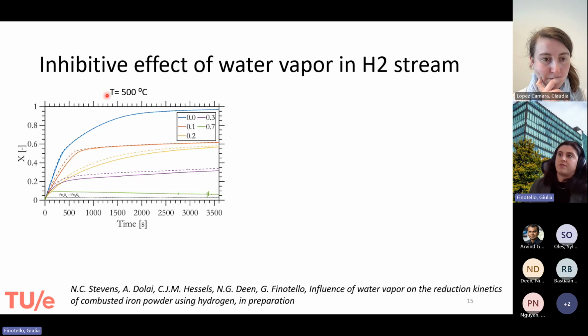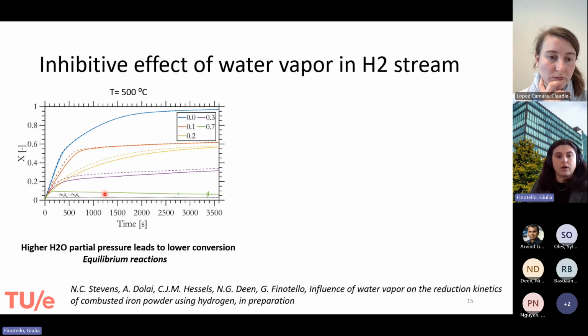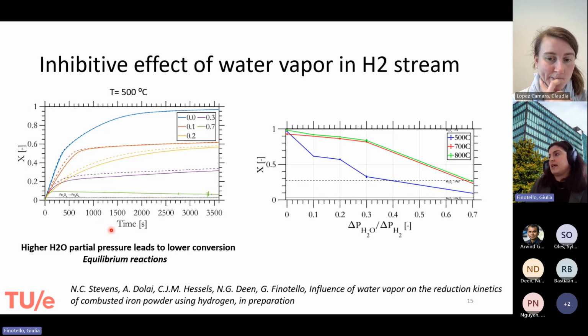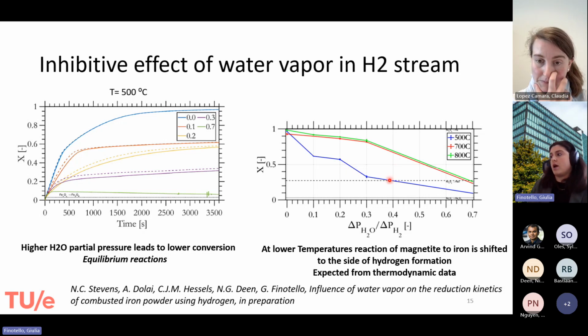So again, you can see at 500 degree temperature, the conversion at different partial pressure of water vapor over the hydrogen. And you clearly see that if we increase the partial pressure, you have a lower conversion because, as I said before, we are talking about equilibrium reaction. And here is the same message. If we increase the partial pressure of the water vapor, we are decreasing the conversion, and this is even more true for the low temperature. You see here at the larger temperature, there is a decrease, but it's not as much as the decrease for the 500 degree Celsius, and this is indeed expected from the thermodynamic data.